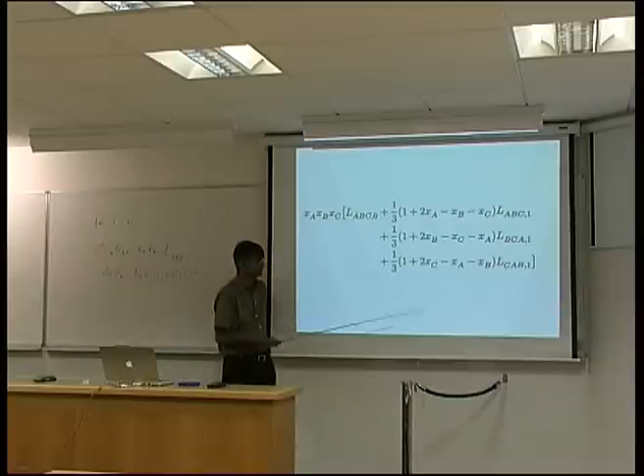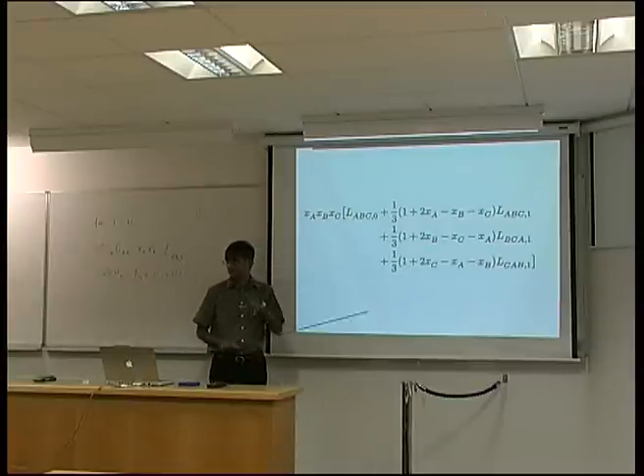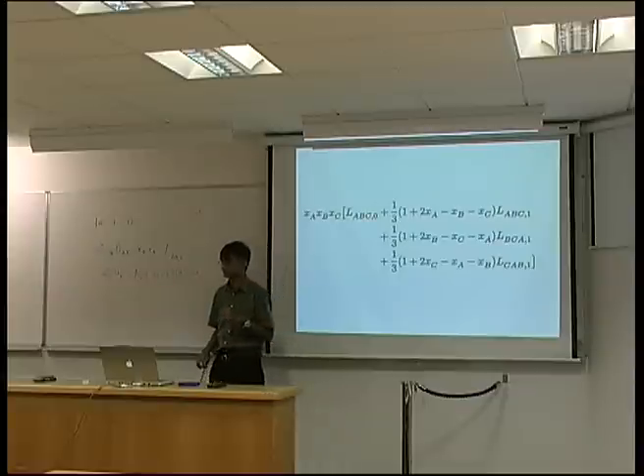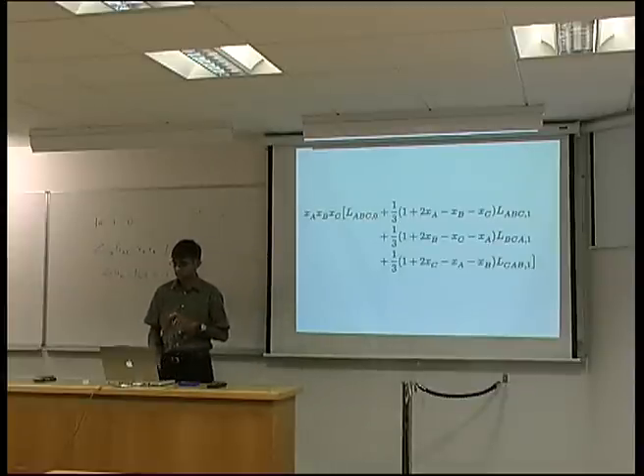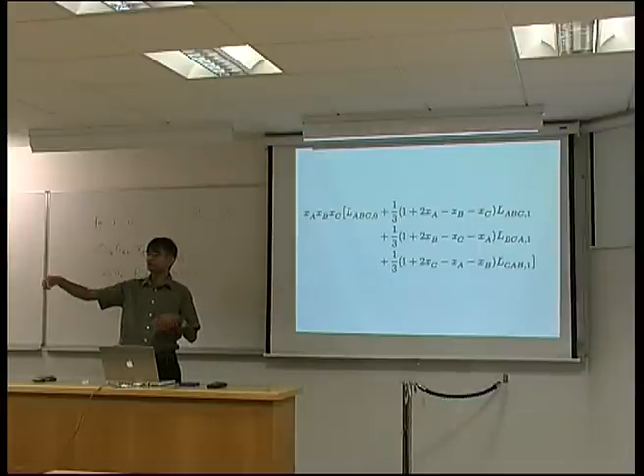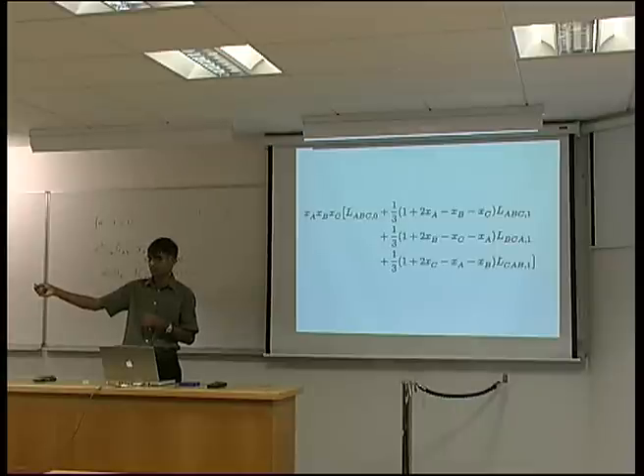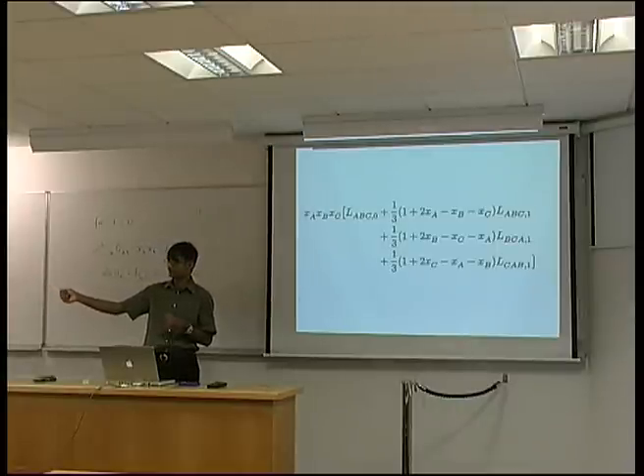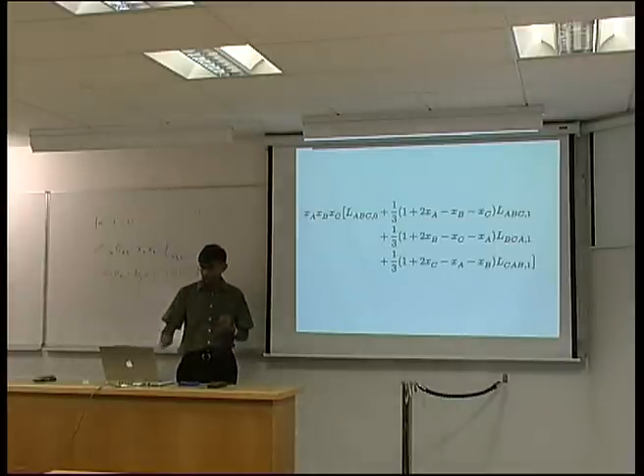So the previous equation is a ternary system where you are only considering binary interactions? Yeah, exactly right. And this one is considering ternary interactions? Yeah, exactly. So this one is an approximation where we are extrapolating from binary systems and hope that our ternary calculation is correct. But if you have experimental data, you might actually have values of these coefficients and this would be a better way of doing it. But you don't have that luxury sometimes. And the best you can do is extrapolate. But once again, we have designed this so that if you modify one of the coefficients, you don't have to modify everything else. And you can see now how we go to higher and higher order interactions. Yeah? OK.